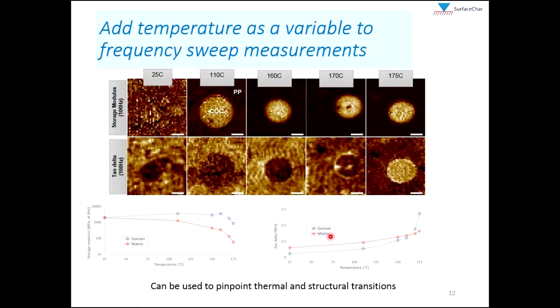And so down here you can see a plot of the storage modulus as a function of temperature. Here's the loss tangent as a function of temperature at a fixed frequency for the two materials, and you can see how here the storage moduli diverged and here the loss tangent crossed over. But again, being able to make these measurements as a function of temperature provides us with the ability to pinpoint these thermal and structural transitions that these viscoelastic moduli are known to do.